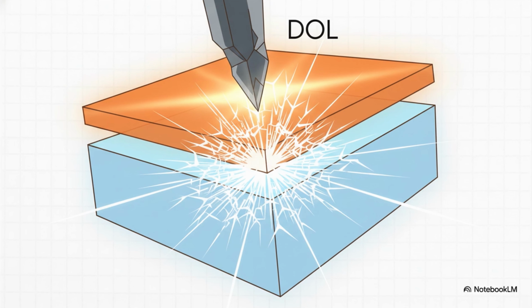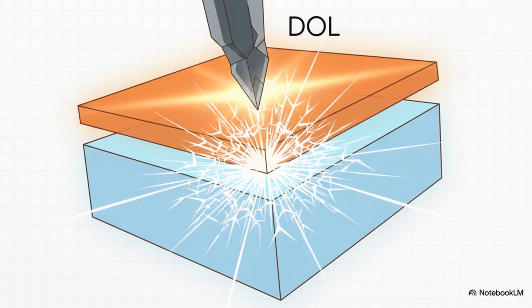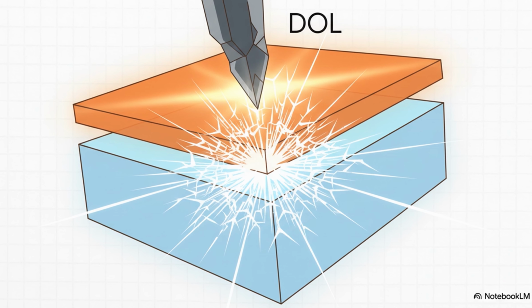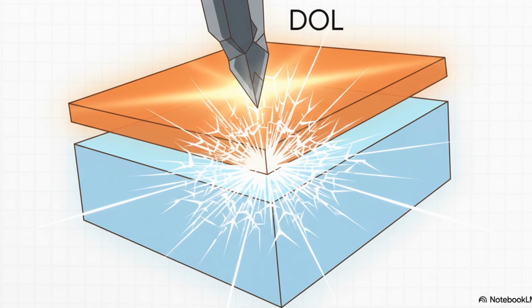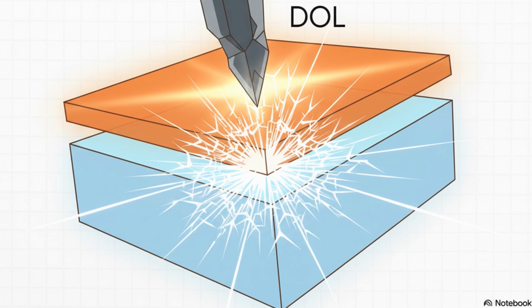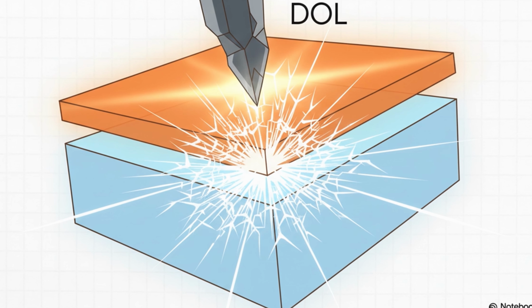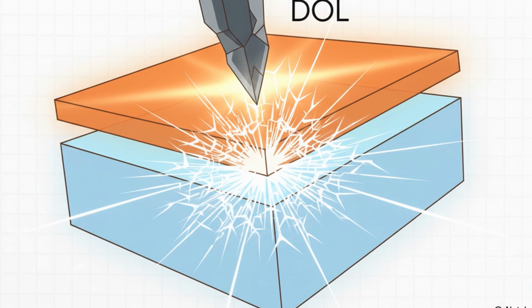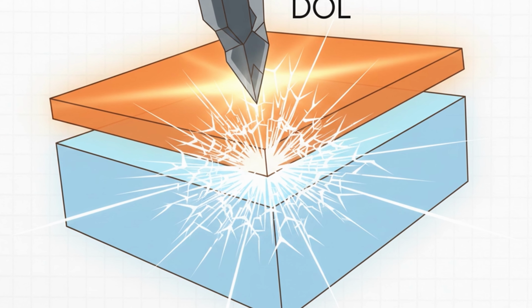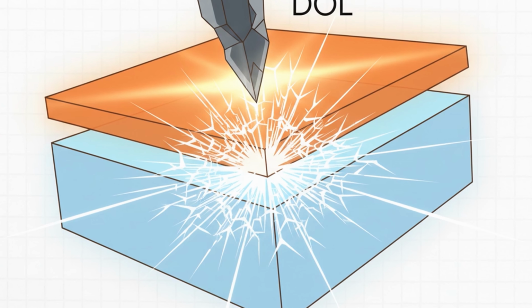So if a scratch or a flaw in the glass is deep enough to pierce all the way through that depth of layer, it reaches the unprotected, vulnerable core of the glass underneath. And when that happens, all of that stored up compressive energy is released in an instant. And that's when you get that familiar, catastrophic spiderweb shatter across your screen.